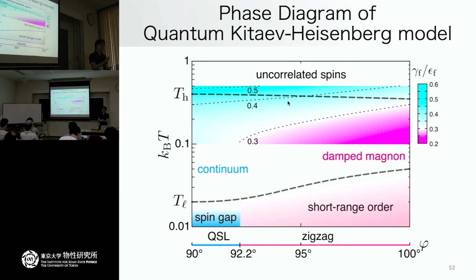If you compare with the heat capacity, the temperature dependence of the heat capacity from the ab initio Hamiltonian for the ruthenium chloride, the experimental result doesn't match with the ab initio result. The temperature scale is quite different, even if you look at the high temperature peak. And there is no separation in the entropy. There's no half plateau in the entropy. We shouldn't have, but anyway, there is a big difference.